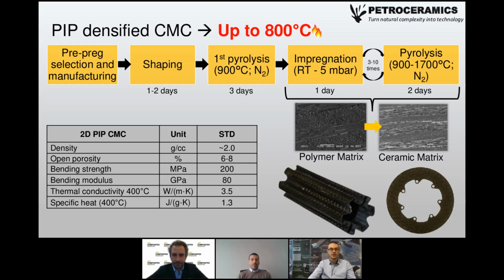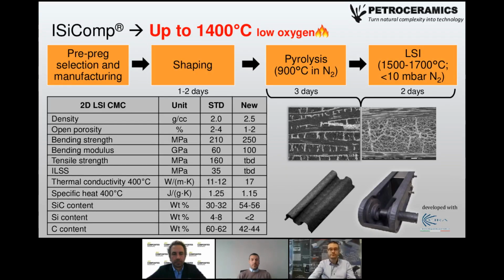In the box on the bottom left, you can see some characteristics that we can achieve in our fully densified composite. But as I mentioned before, we could get more porous and lighter objects and also with different thermal properties. And we can tune these characteristics by changing the number of PIP cycles and by changing the temperature of pyrolysis, basically.